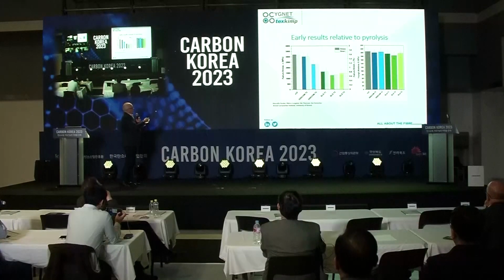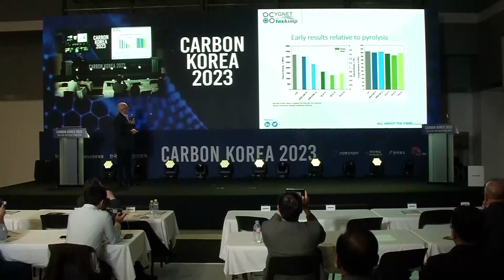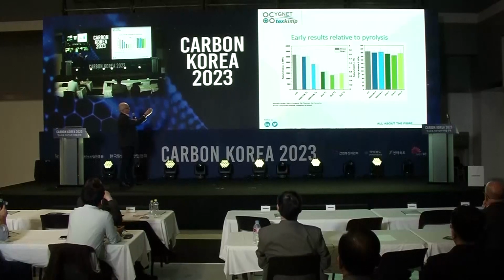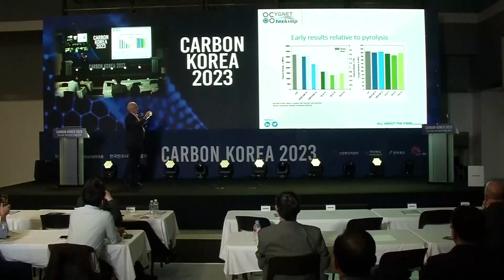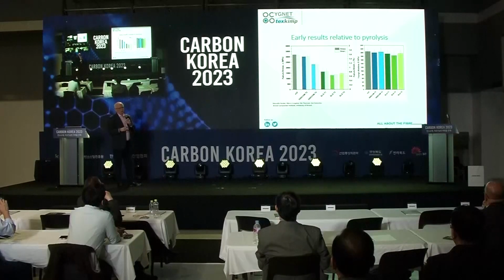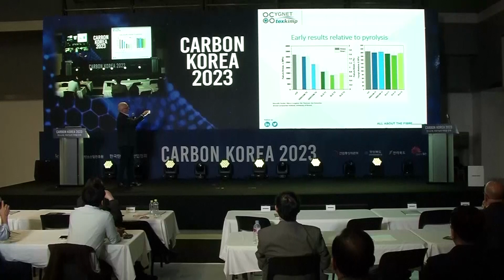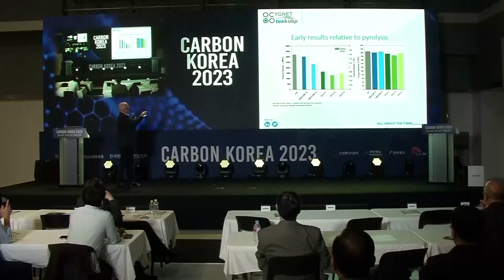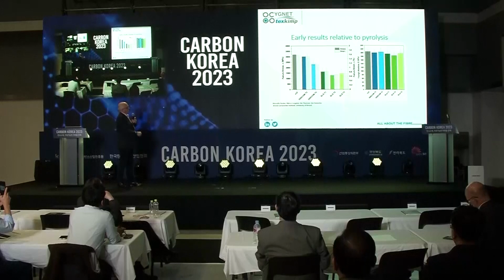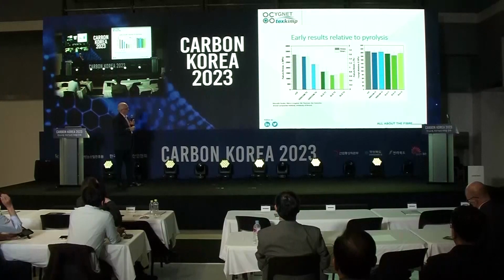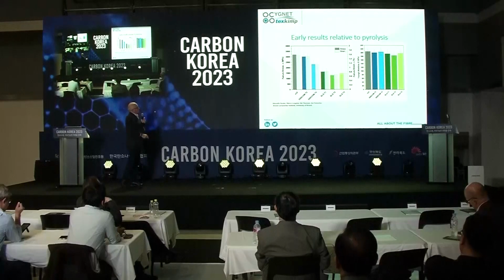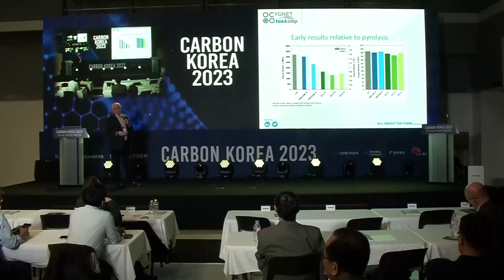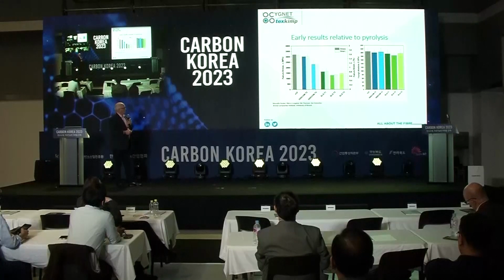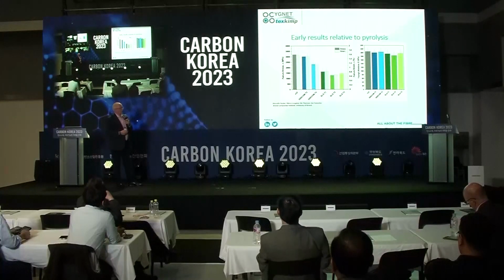So some of the earlier results relative to pyrolysis show basically what we might expect. On the right, you've got the modulus, and even with pyrolysis and our system, the difference in modulus is negligible. But of course, you do see in pyrolysis a drop-off in strength. You'll see the virgin on the left, then our system, and again, we've gone through several iterations to get comparative results. And you see we're not too far off in terms of the strength there. Those were early days. We anticipate getting much better results as we progress.